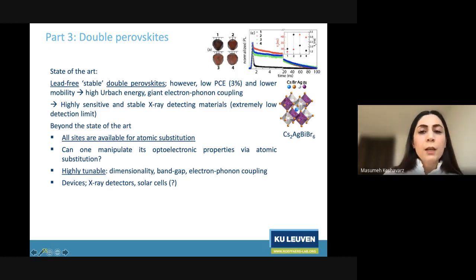Why double perovskites? They are lead-free, first of all. There is no lead in them. They are more stable compared to the single perovskites, but there is a drawback that their power conversion efficiency is not so high in solar cells. And that is attributed to their high Urbach energy, giant electron-phonon coupling constant, and so on, and low mobilities also. However, their application in X-ray detection has been proven to be very, very efficient, and they are very sensitive materials to X-rays, with higher sensitivity than ever reported.